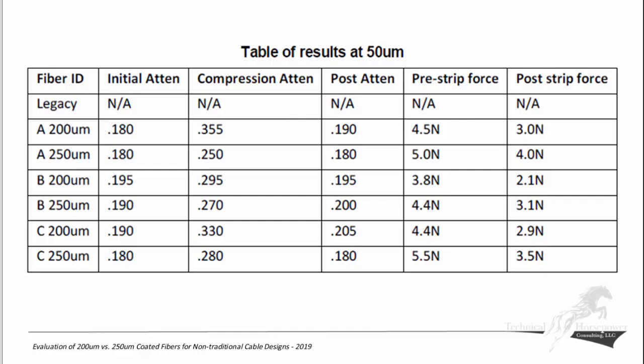There we go. This is at 50 micron, and here you'll see that we didn't even include the legacy fiber because at the 50 micron compression, the fiber didn't survive. Clearly an indication that our coating systems have improved significantly between 10 years ago and now. And again, the results between the two were a little more aggressive, but not significantly. Next slide, please.